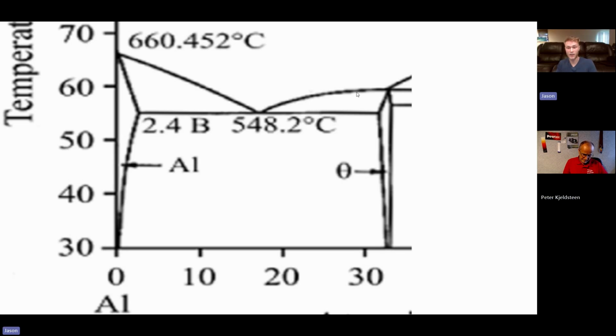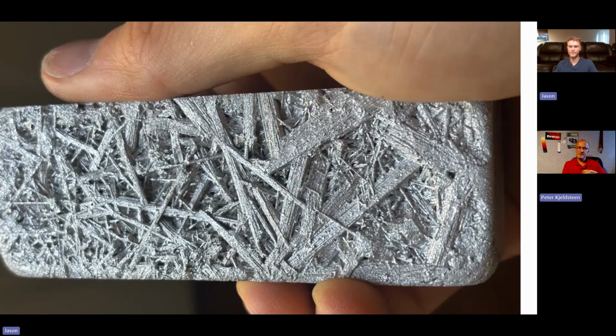And then as you cool any alloy, you have solidification, densification, right? Because liquids have a larger volume than solids generally. And so as the melt cools, the liquid pulls away from the surface. It's hard to illustrate this with just words. But if I were to have an intermetallic rod that formed on the surface up here, and then the liquid pulled away from that rod as it solidified, that rod would now be elevated, and you could see it as the liquid receded from it. So it'll be dry, even though you are at the melting temperature. And that's what you see here.